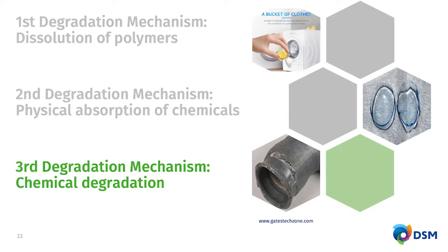The third, degradation mechanisms, is the most important, and I think most of you know about this: chemical degradation. As an example, I show here a plastic hose that is used to channel hot engine oil. After a certain period of time, you see some cracks on the surface of the plastic hose, as well as embrittlement at the surface. When you do a proper analysis at the surface, you will see that the surface is composed of lower molar mass plastics compared to the original plastic before aging.